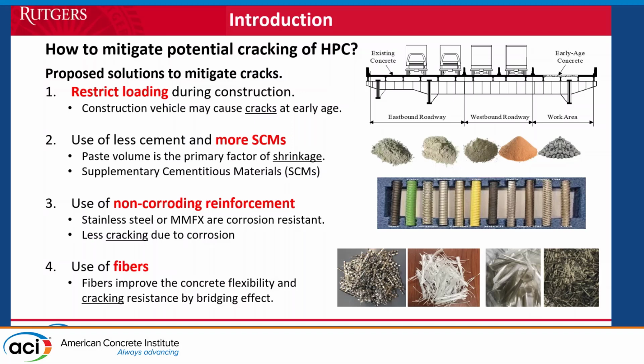So there are other things that we needed to do, and that led us to design mixes we call high early strength for the first 6 to 8 hours. We ended up using different types of rebars. We used, for example, and also experimented with in a project, the MMFX steel. This is one of the best performing rebars in the study that the Turnpike did compared to all rebars that we have done. And the last part was, what if we use fibers to be able to mitigate some of the cracking that we have no control of?